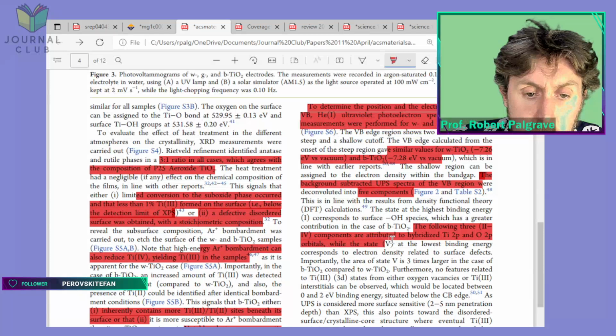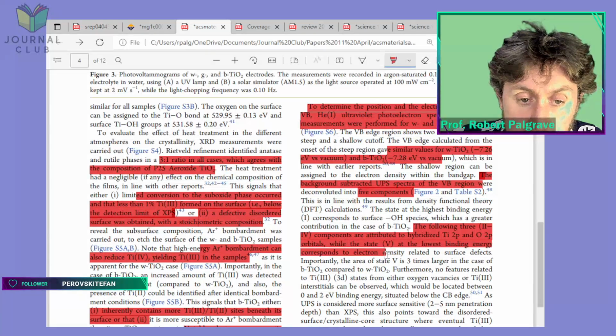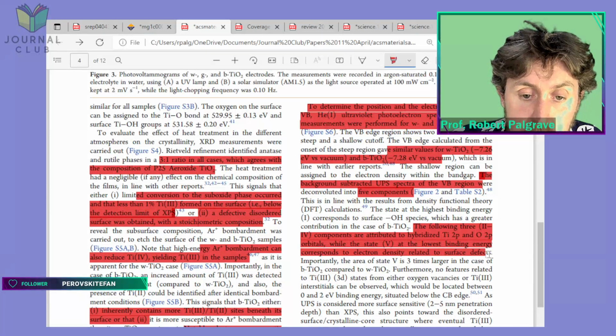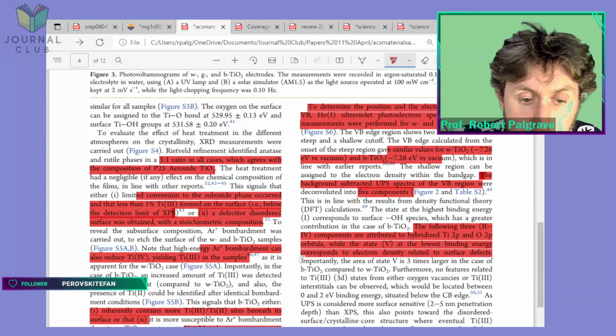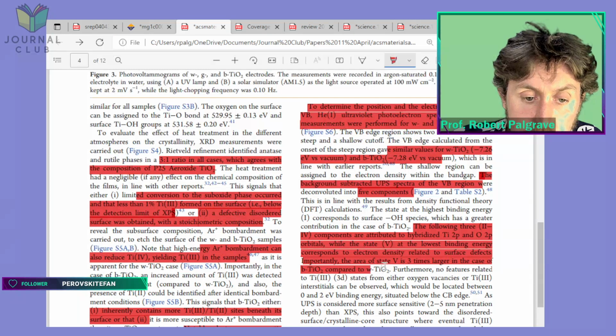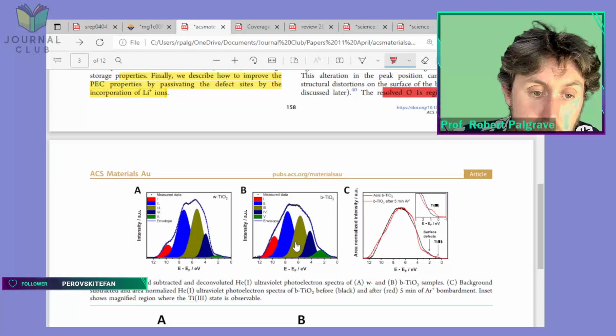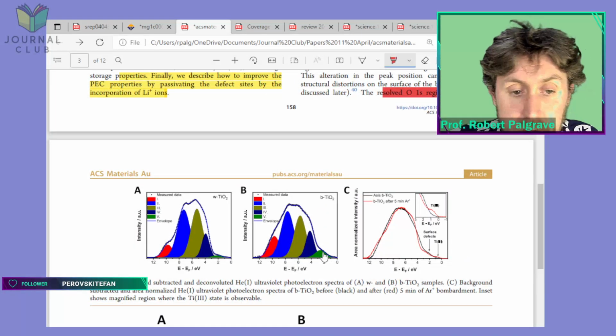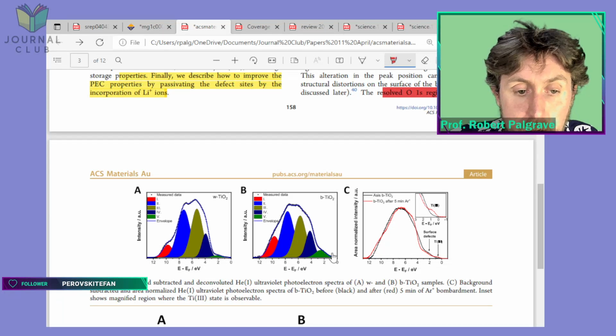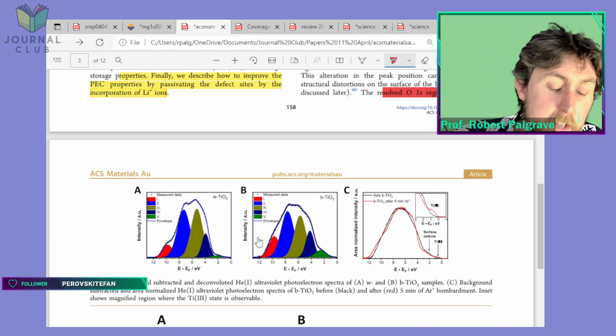while the state at position 5 at the lowest binding energy corresponds to electron density related to surface defects. Importantly, the area of state 5 is 3 times larger in the case of black TiO2 compared to white TiO2. Okay, let's go have a little look. So they're talking about this. Okay, they're talking about this green thing here, as being surface defect states.